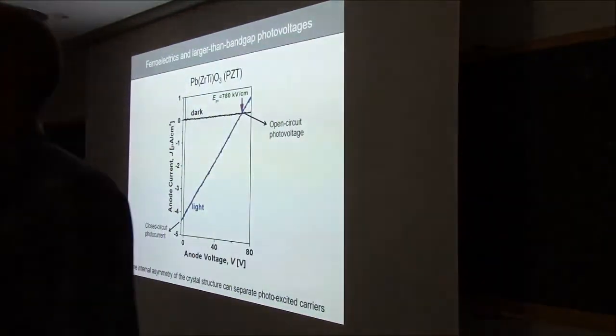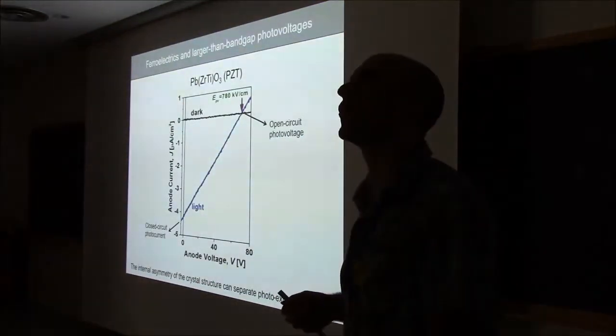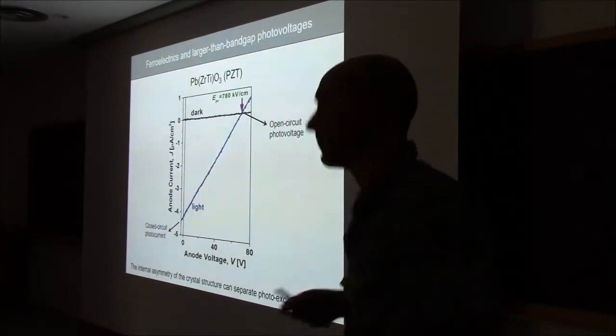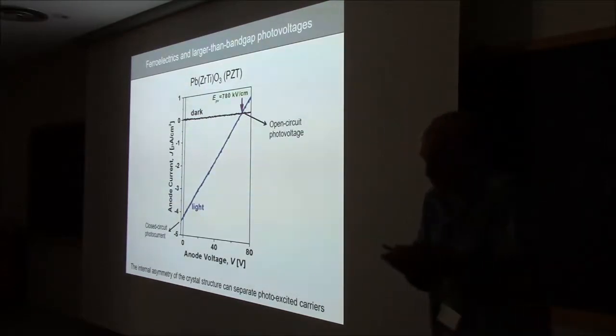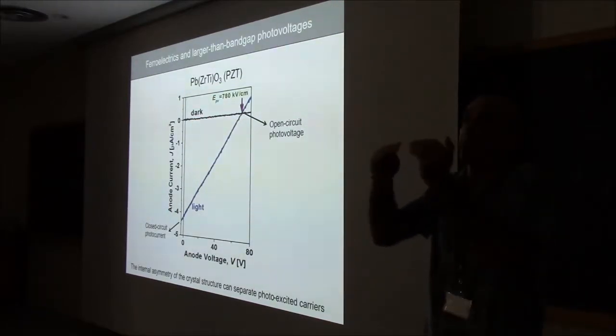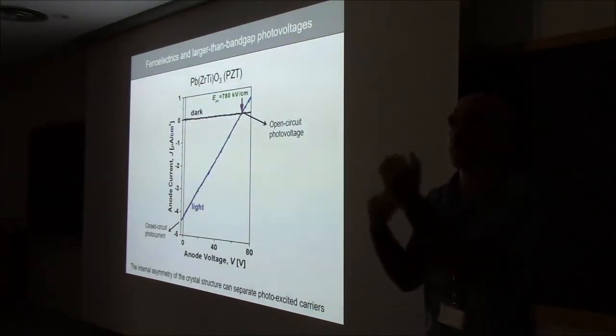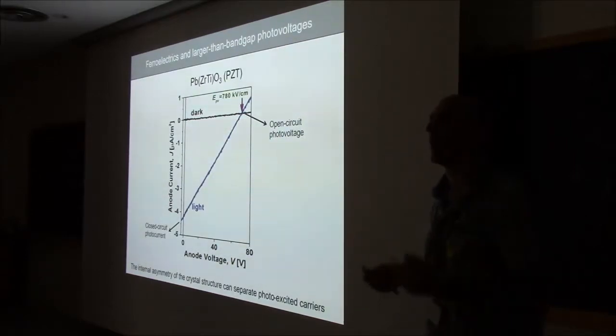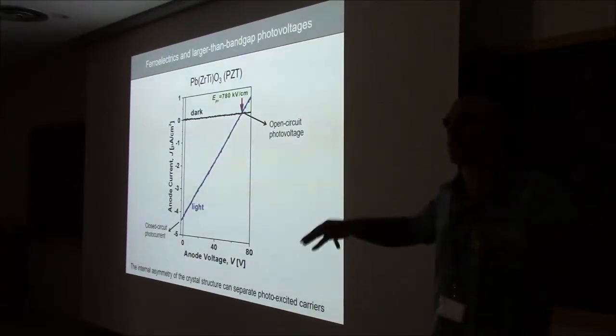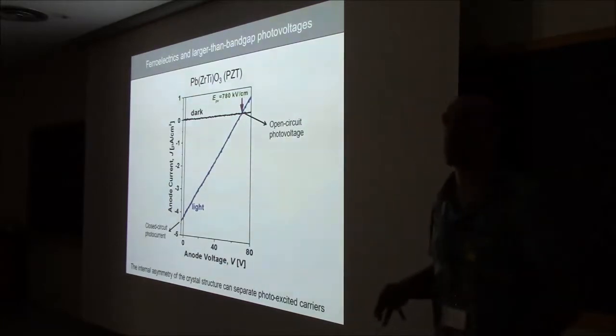Yes? Would we expect some short circuit current by shining a below band gap light? Would I expect a short circuit current? I guess yes. Yes, partly it will be small, but you could get it for a couple of reasons. One is that you have some defects that locally, some defect states, and the excitation energy for those defect states is much less than the band gap. So for oxygen vacancies, it's typically 1 eV. That's one thing. The other thing is your light is never perfectly monochromatic. It has a tail, so maybe the spectral tail can reach into the band gap too. So yes, you can measure some current, but it will be pitifully small.